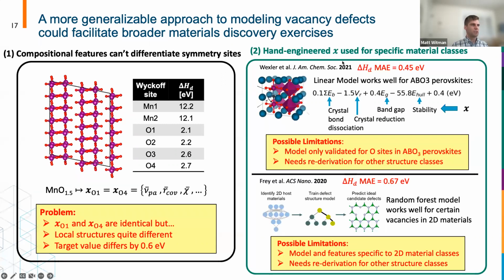So there's been some really interesting recent work to model these defects with much higher efficiency than DFT. This recent paper derived a very interesting linear model based on hand-engineered features that account for some of the structural information, so that they were able to predict oxygen vacancies with a pretty good mean absolute error, and it's validated in these ABO3 perovskites. But this kind of hand-derived linear model won't work for the cations in this crystal structure, and you would probably need to rederive this expression if you move to a different structure class, for example.